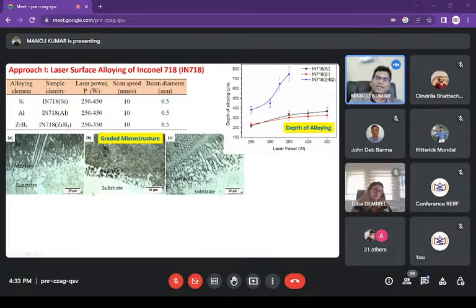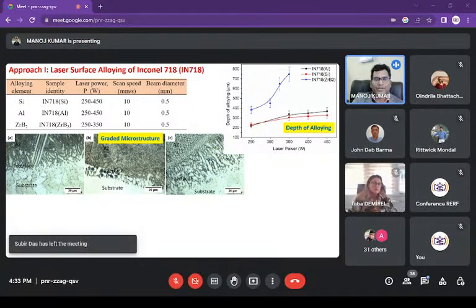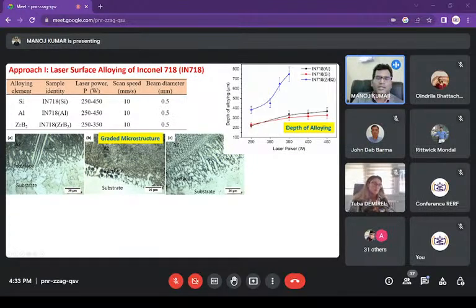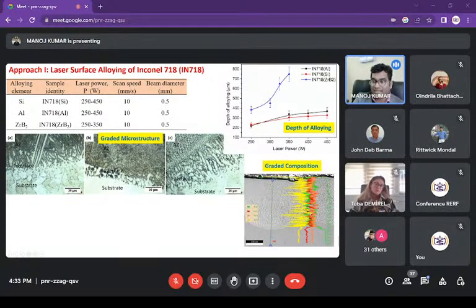Now we got a graded microstructure. So this is the alloyed zone, where we have developed an altogether different zone by alloying, where the aluminum or silicon is alloyed, and this is the unaffected zone, the substrate zone. And you can see the interface. We have a totally intermetallic structure in the alloy zone and the interface joining the alloy zone to the substrate, and the substrate remains unaffected. So we have the substrate, then the interface, then the alloy zone. So there is a gradation of composition.